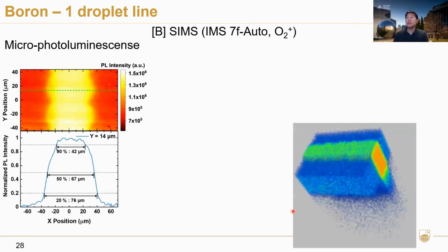If you use SIMS measurements, in this case done using the Cameca IMS 7F Auto with O2+ as a primary ion, we see this really nice 3D map of the boron distribution within the printed area. I should probably point out this is not to scale, so the z-axis has been extended quite a lot. But essentially we see that it's quite localized. We can even see a bit of an interface here, where before the oxide the polysilicon is in this solid region at the top here. And we see a bit of doping into the crystalline silicon afterwards.